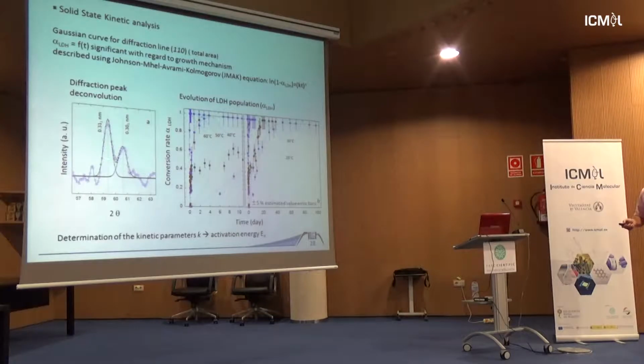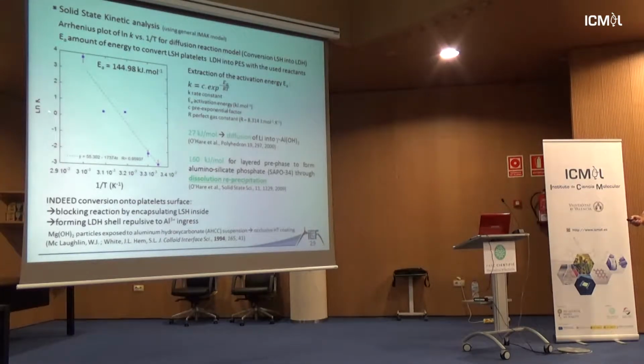And you can, of course, refine the presence of one or the other in some kind of solid state kinetics analysis. It's 1 minus alpha and alpha, so you have a transformation step of one phase converting to another one, LSH to LDH, versus temperature. So you get all this conversion rate, and that's the rate of conversion for LDH. And if you do that in temperature, you have access to the kinetics parameters and, of course, to the activation energy. And if you draw this K versus the inverse of temperature as an Arrhenius type of graph, you end up with an activation energy of quite consistent, more than 100